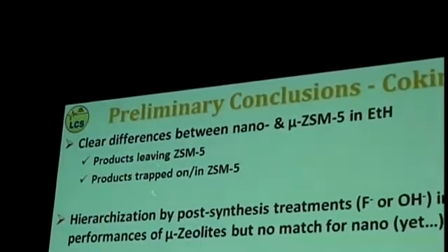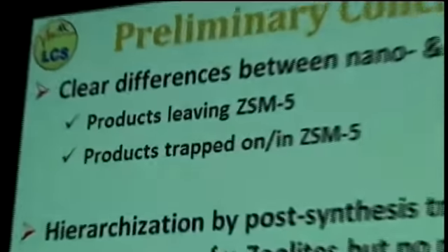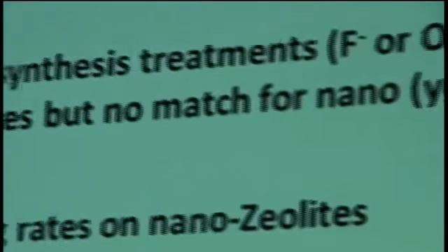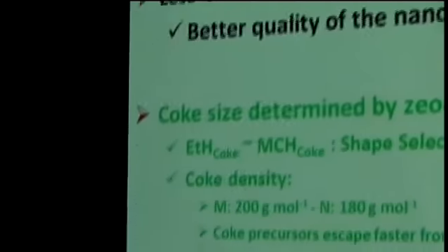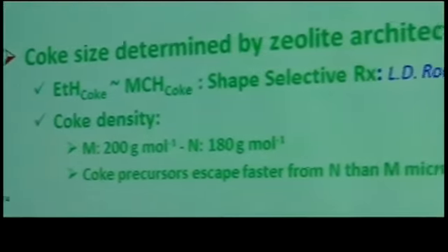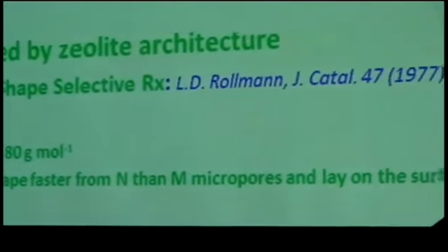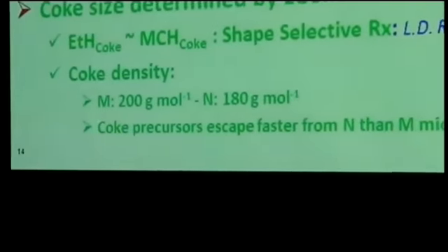So if we try to summarize what we have known so far, there are clear differences between ZSM5, whether they are nano size or micron size, where you have built some mesoporosity or macroporosity by treatment. And these clear differences, we see them by looking at the products leaving the ZSM5, and also by the nature of the products that are trapped on the external surface or inside the ZSM5. Hierarchization by post-synthesis treatment, either by fluoride treatment or by caustic treatment, is improving the time on stream stability of the material, but it is no match for the nano-size zeolite. I mean, there is a clear difference between these two families.